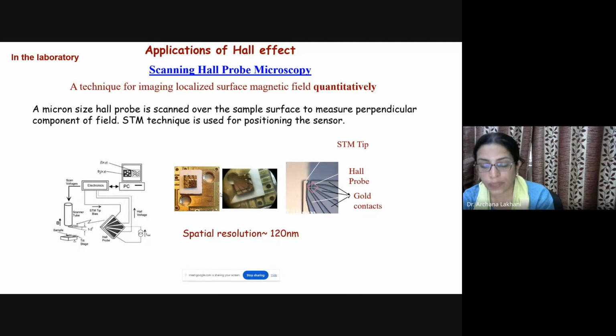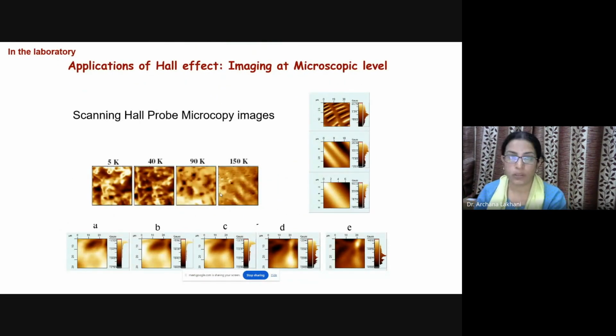Apart from the AFM technique, this is also one powerful technique with which, if we scan the Hall sensor, we can even find out the local magnetization of the sample, which gives a magnetic image also. This particular slide shows the imaging at the microscopic level for a hard disk. And this is one sample in which we did this at different temperatures, which shows that at 150 Kelvin, it has a totally different orientation. Suppose it is antiferromagnetic, and the black shows the ferromagnetic at low temperature. If you see, the black spots are enhancing.